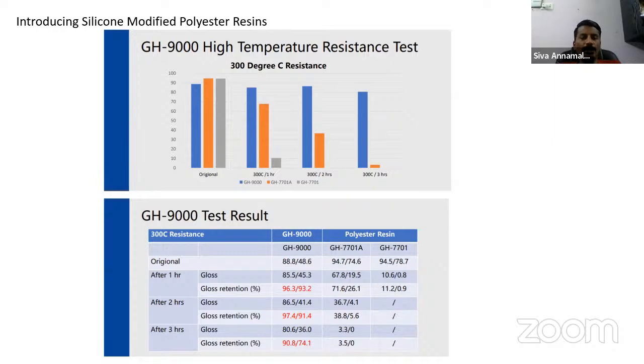Okay, so we expose the normal polyester, with viscosity about 10,000 to 20,000. The gloss retention is very poor, whereas this silicone modified polyester resin has extremely good gloss retention even after 3 hours of exposure at 300 degrees Celsius. So the question may come, how do we believe? What kind of testing can we do? Whether this is really better than the conventional polyester system.